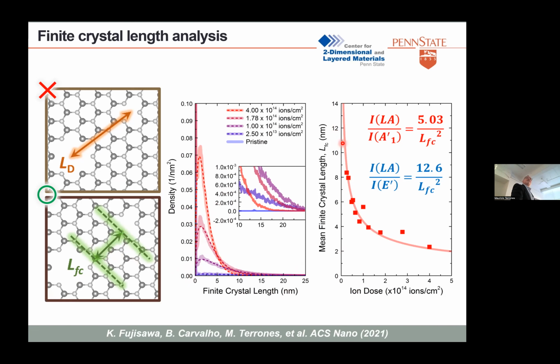This is basically the mean finite crystal length against the ion dose, and we can then correlate with these formulas the intensity of the LA and the E prime peaks. So if you know the intensity of the LA peak and the intensity of the E prime peak, or the A prime peak, then you can know the finite crystal length if you use those formulas. For tungsten disulfide, we have a similar thing. It's a similar equation, but not the same values. So this is a good crystal, right? This has very few defects in this regime, but if you have too many defects, then you are in here. That's something that can be used for predicting how defective your system is before you even try to do anything with it, especially with CVD grown materials.